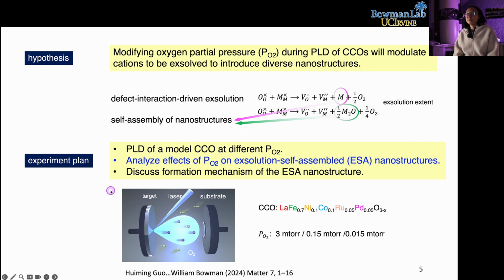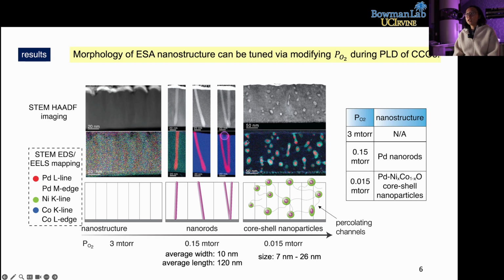To prove this hypothesis, we use three different oxygen partial pressures during the PLD to introduce the exsolution self-assembled nanostructure: 3 millitorr, 0.15 millitorr, and 0.015 millitorr. The model CCO we use is a lanthanum ferrite doped with nickel, cobalt, ruthenium, and palladium at the B site. You can see the formula here. The goal of this experiment is to analyze the effect of oxygen partial pressure on the exsolution self-assembly nanostructures. Also, we will discuss the formation mechanisms of these nanostructures. The STEM images and the corresponding element mapping show very interesting, different nanostructures at each thin film depth at different oxygen partial pressures.